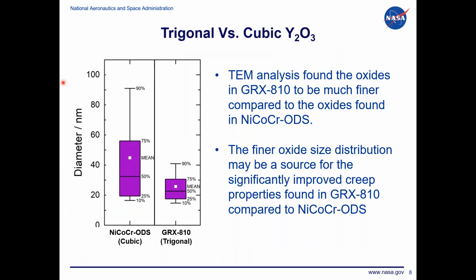And when you're making an ODS alloy, the goal is almost always to try to get as much nanoscale oxides as you can that are as fine as possible. You want them to be maybe even 9, 10 nanometers in diameter. The finer, the better for creep properties. And when looking at all this TEM characterization, we started measuring the oxides that we saw in the nickel cobalt chrome base ODS alloy and in GRX 810. Again, the different crystal structures. And what we found was GRX 810 had a significantly finer oxide distribution than what we saw in the nickel cobalt chrome ODS. And so this might be a result of just having this different type of crystal structure.